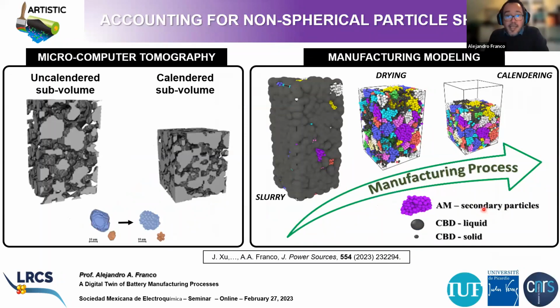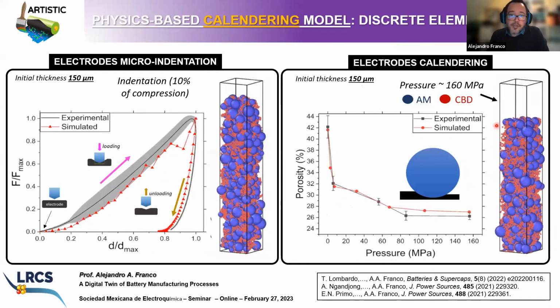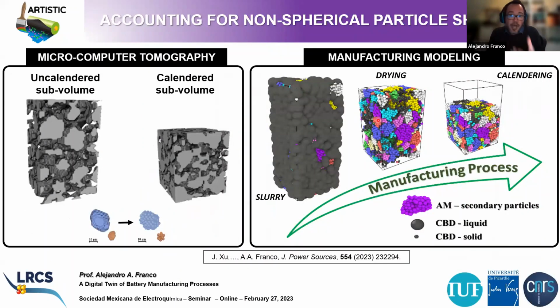We have recently extended this model. This is a paper published very recently this year, to the case of having non-spherical active material particles. Because probably you noticed that all the simulations I showed you so far with the physics-based approach are considering active material particles as spheres, right? But in reality, this could be a quite good approximation for active materials such as NMC111. But if you start to look in detail at the particle morphologies, you don't have spheres, right? You have things like that, right? Which could be represented eventually as spheres, but they are not really spheres, right? So in order to be able to simulate the systems, the hypothesis of the spherical particle is very far away from reality.